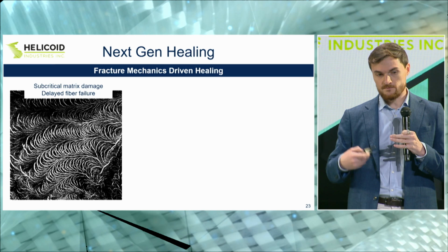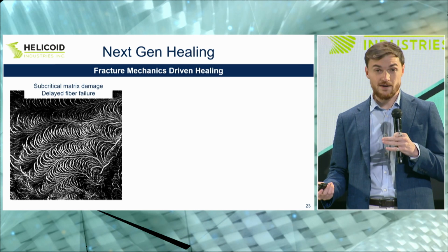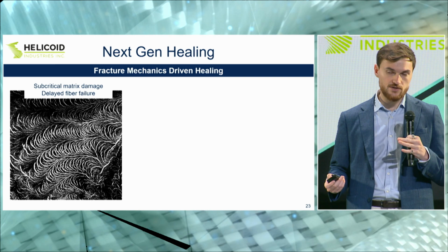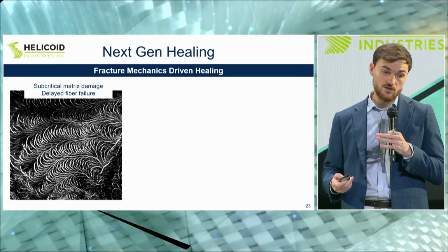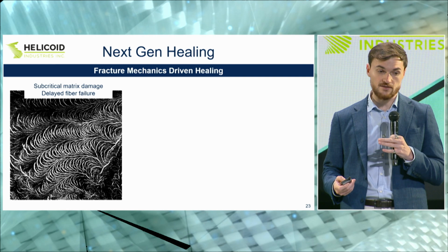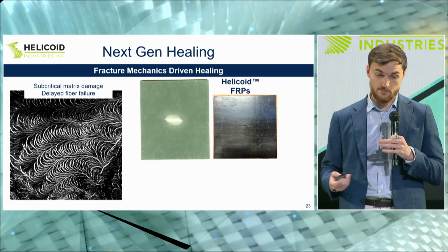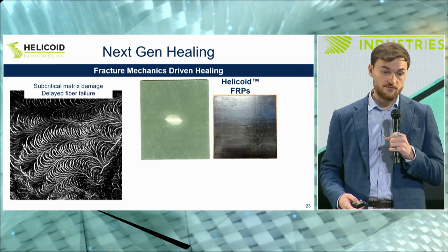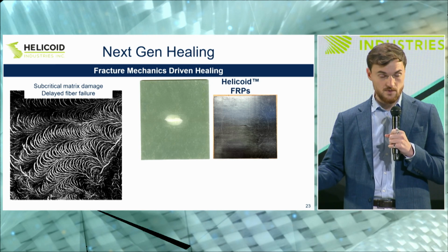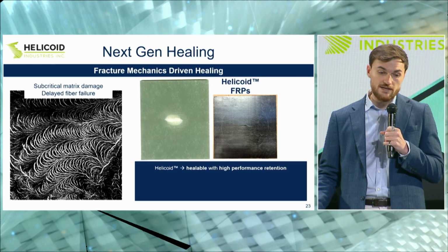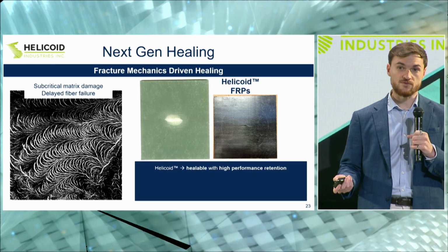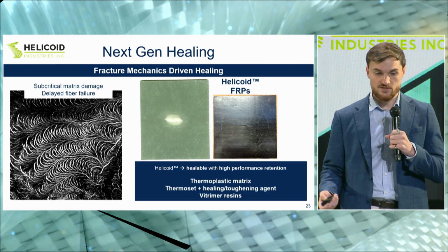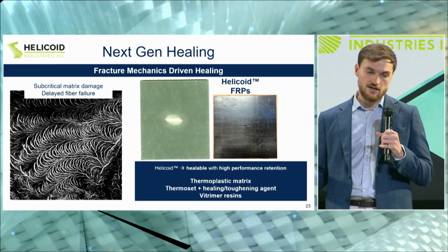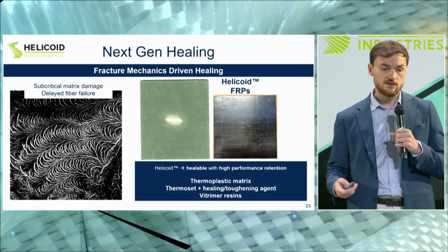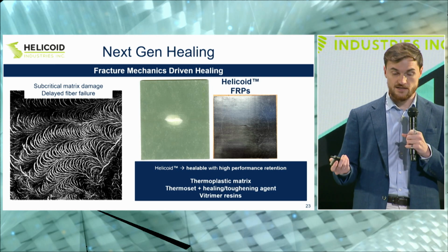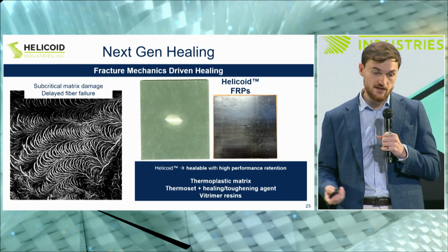In our case, with our fiber architecture, by dissipating damage through only matrix failure, and delaying, or in some cases avoiding completely the failure of the fiber, like in the samples that I showed you for the glass phenolic reference and the carbon polypropylene sample, you could really achieve a healable composite with a high performance retention. And then it's just a matter of using a resin that you can heal or reprocess, whether it's a thermoplastic, a thermoset with a healing/toughening agent, or new resins like vitrimer resins.